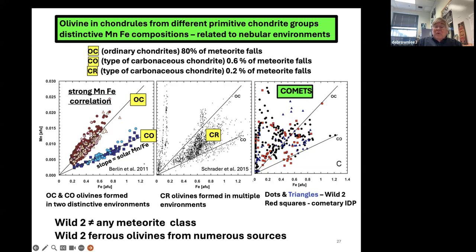One is the actual Wild 2 measurements, and the red squares are from a comet, what we believe is a cometary interplanetary dust particle. They both show fantastic scatter, with no tendency at all toward any correlation, and they fill areas not seen in the two plots to the left, the so-called forbidden triangle.